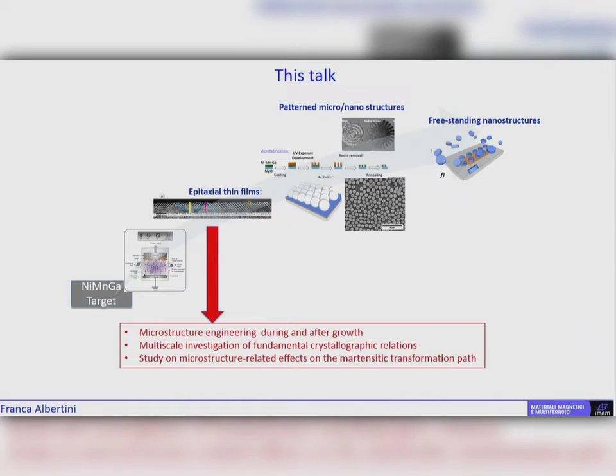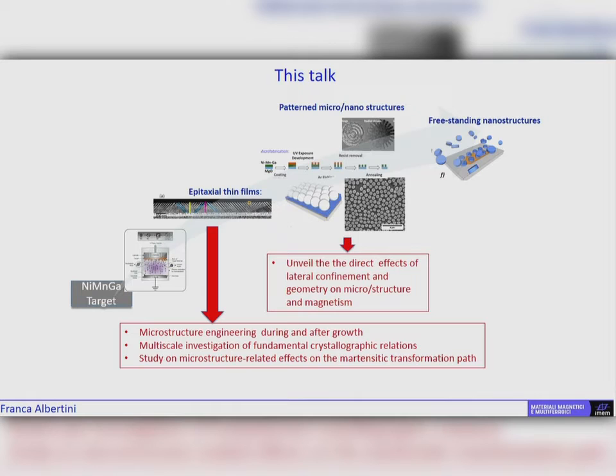what we have done from thin film, we have engineered the microstructure during growth and after growth, and we have made a multi-scale investigation of fundamental relations and studied microstructure-related effects on the martensitic transformation path. Then the patterned structures have been mainly produced to unveil the effect of lateral confinement and geometry on microstructure and magnetism of these materials. And as for the freestanding nanostructures, we have studied the effect of substrate release, and also we have verified a magnetothermal actuation of these freestanding materials.